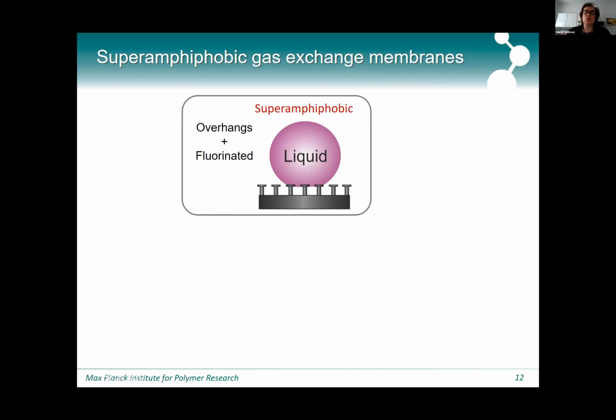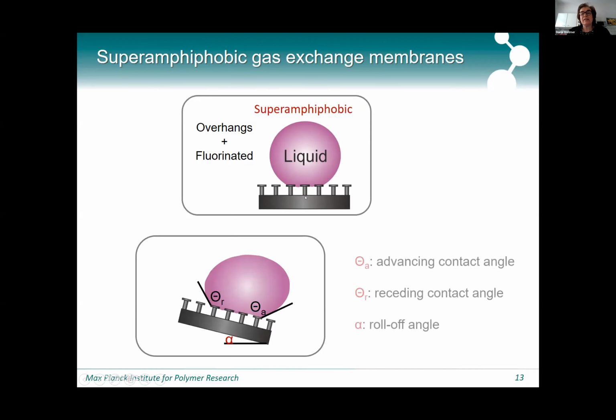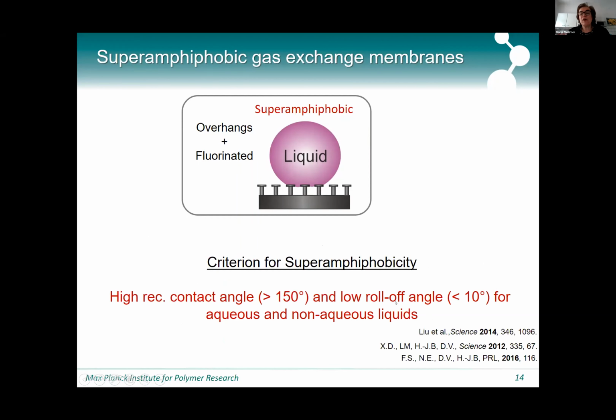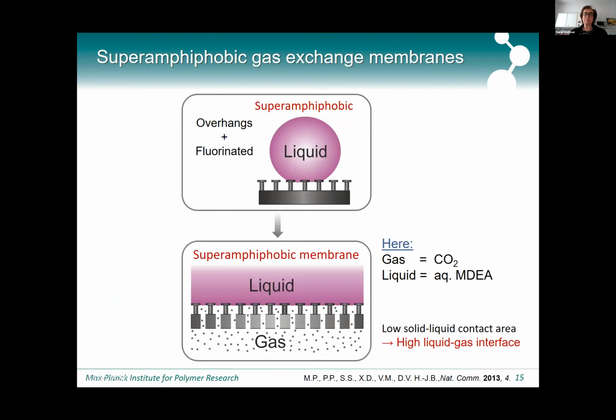And therefore, we wanted to investigate the concept of superamphiphobic coatings. As already mentioned by Dan, superamphiphobic coating requires surfaces containing overhangs and fluorination, and they are characterized by a huge advancing and receding contact angle, and the droplet rolls off as soon as we tilt the surface by, roughly speaking, 10 degrees. And this holds for both aqueous and non-aqueous liquids. So now we designed membranes with the idea that the liquid can stream on one side of the membrane and gas on the other side of the membrane.